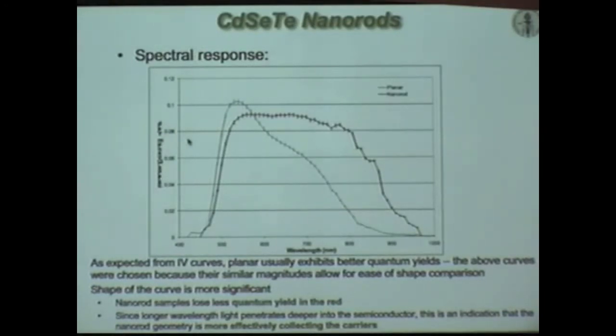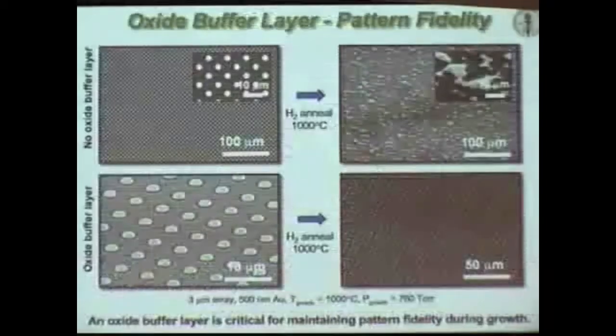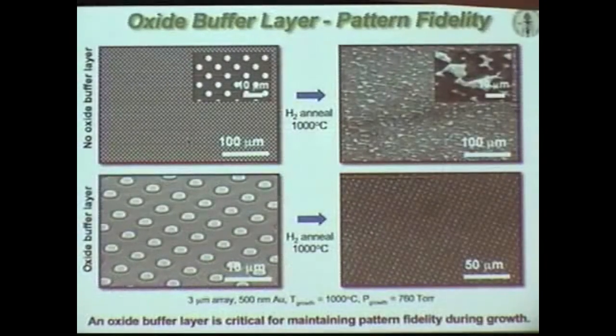But the exact same material grown the exact same way in the radial morphology collects carriers from the band gap all the way through as if you had them all the time, because they only have to move within their diffusion length sideways. Okay, so that's good. So cadmium selenide telluride's below the line. For time purposes, I'm skipping a lot of work.